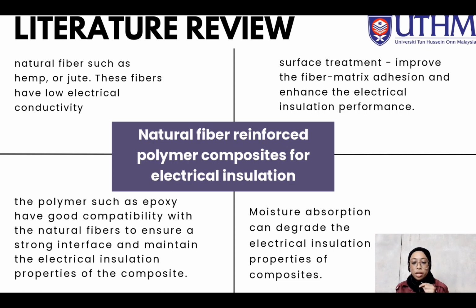For the choice of polymer, researchers usually use epoxy polymer because it has good compatibility with natural fibers to ensure a strong interface and maintain the electrical insulation properties of the composite. After the natural fiber and this polymer are combined or blended, it will enhance the electrical insulation performance. Other than that, to increase the electrical resistance, we decrease the moisture absorption, so that it can work properly for electrical insulation.